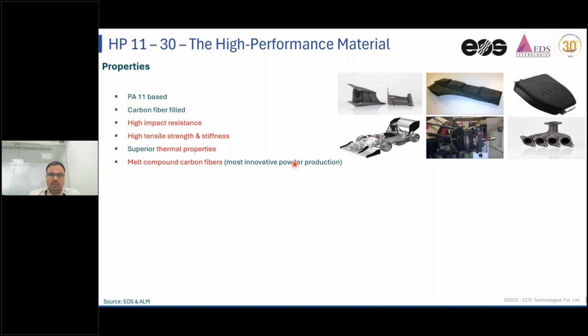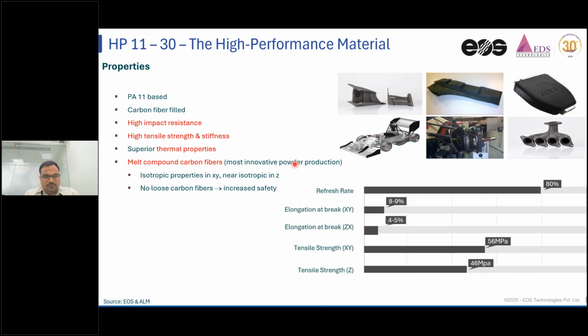As a basic composition or basic polymer, it is a melt compounded carbon fiber, which has the carbon particle melted in it and then compounded. So at the end of the day, when you fuse your powder into the physical part, you get more promising properties along with the carbon particles that are there, which are superior, or I would say better than the other carbon fiber composite materials available in the 3D printing industry. And they are quite isotropic in XY orientation.